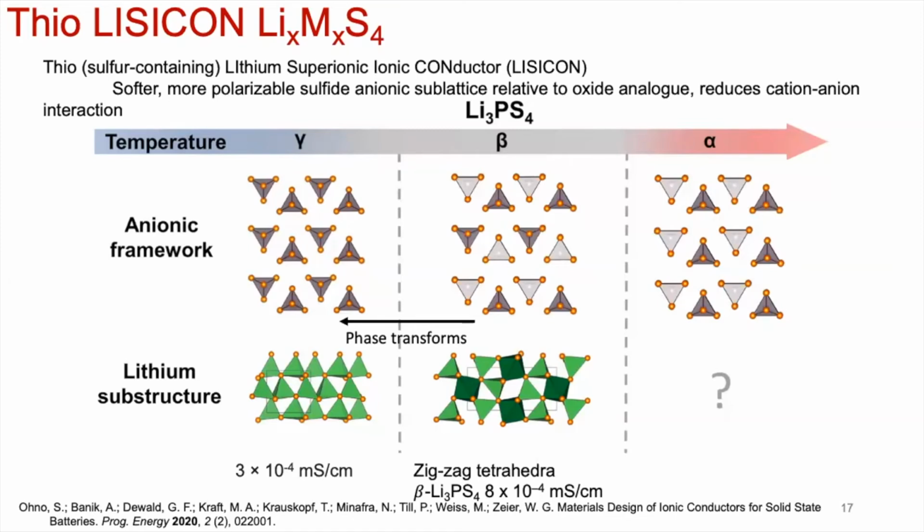But what that's telling us is that if you can create this sort of polyhedral disorder, you can increase ionic conductivity. So then you go back to your 230 space groups, 200,000 compounds in the Inorganic Crystal Structure Database, and you ask, can I find substructures within different families of compounds that have something like this, where you just increase the temperature, trap this phase somehow by different synthetic methods, and then get to a higher ionic conductivity phase?